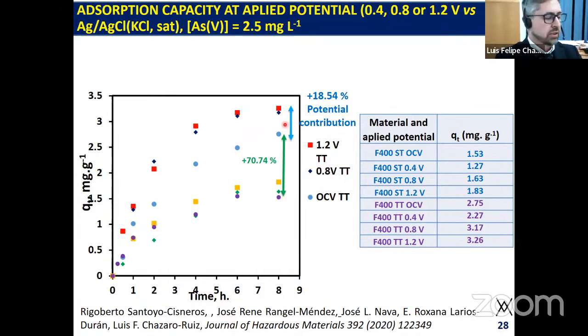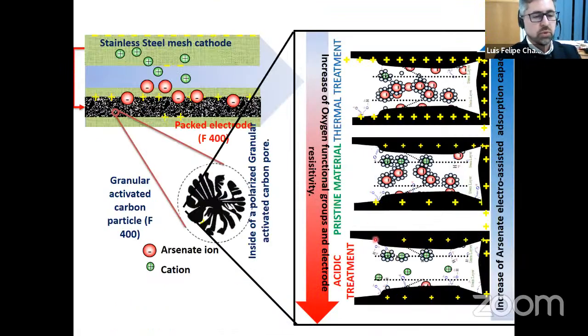No? So then, this is an important performance of the electrode. And in conclusion, we can see that the higher the degree of oxidation of the material, the higher the electrical resistance and the less available polarizable area, which also has an impact on a lower absorption capacity of the arsenate, no? In contrast with this electrode.